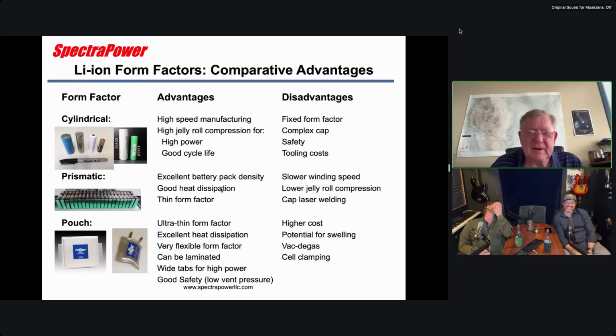Yeah, so it's just like airplanes, right? It takes a while to figure it out. In between, you have a few accidents. So that's those advantages. They're slower to wind because you have a flat mandrel, and I can talk about that more. You don't get the high compression because it's a flat pack, and you have to laser weld the cap. Cylindricals, typically the cap is crimped, although you can laser weld them. But laser welding is more expensive. But in a prismatic, you don't have a choice. You really have to laser weld it.